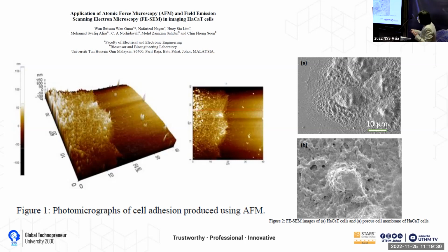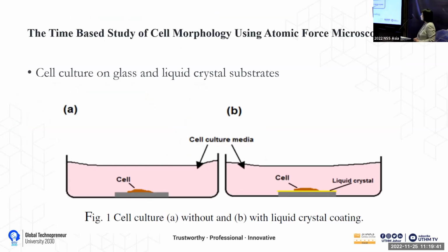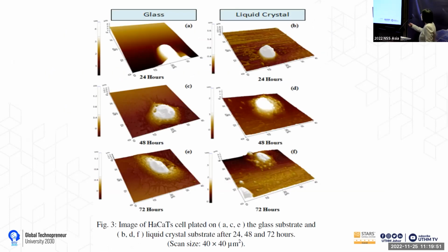So the thickness of the cell you can see from here is in nanometer, whereas the FESEM cannot give you that. So this AFM already complemented the images obtained from the FESEM, right? So how about application of biomaterials to study the interaction of cell and the biomaterials? We look at cell adhesion on the glass substrate, also cell adhesion on the liquid crystals. Right, so we found that if you expose a cell to different substrates, glass and liquid crystals, over a time frame, you can see that the cell actually moves over the glass and spreads.